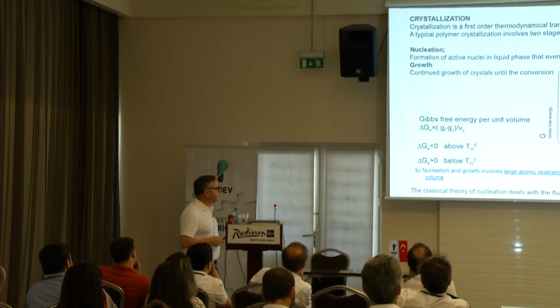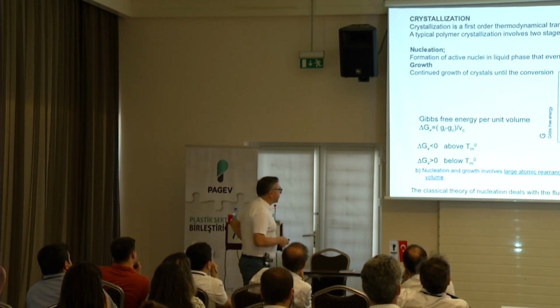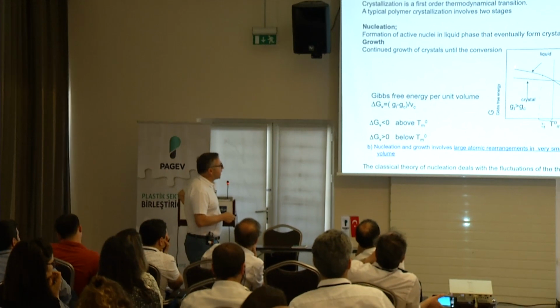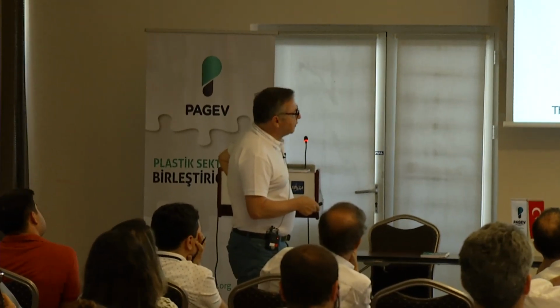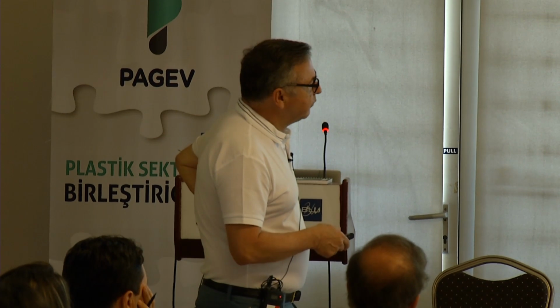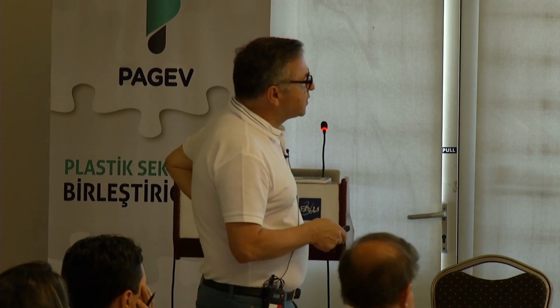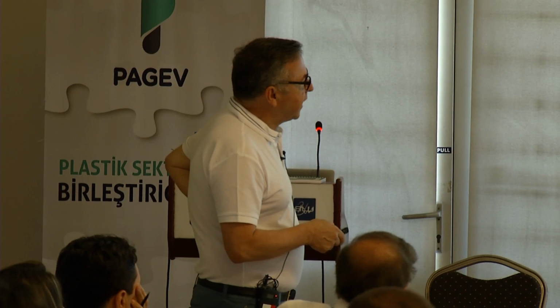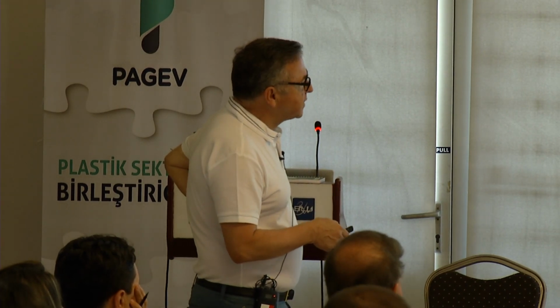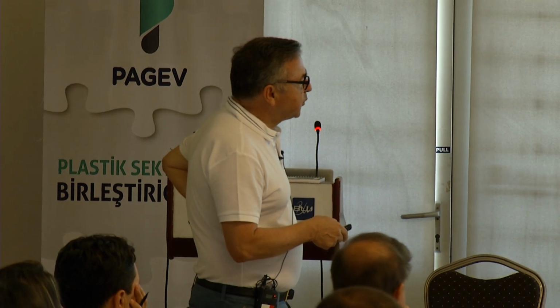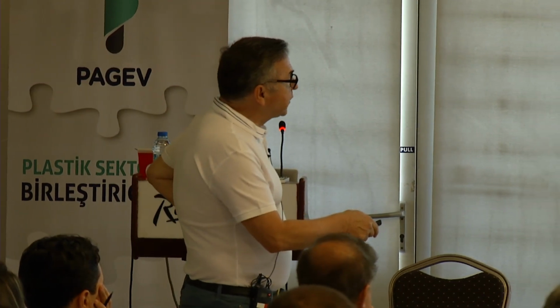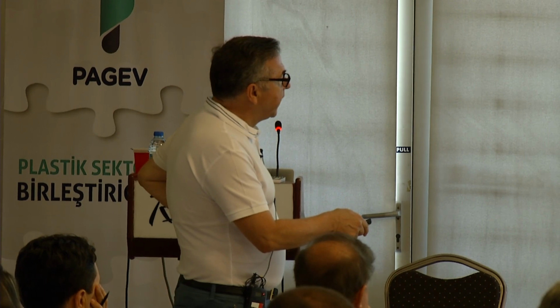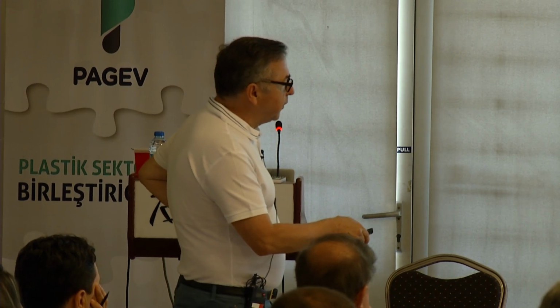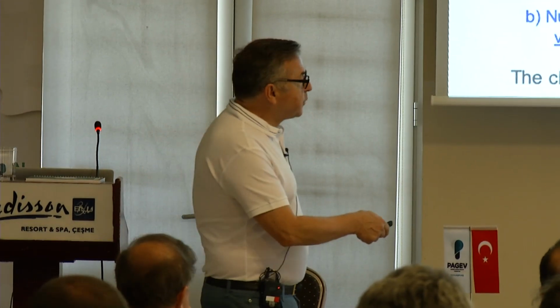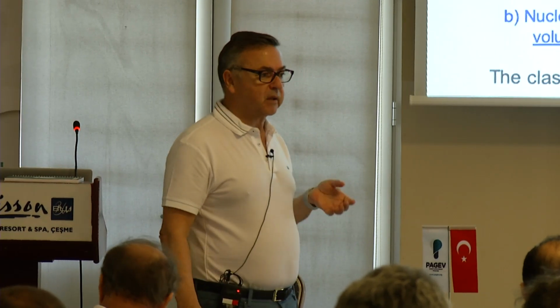So free energy is a very simple concept. The typical polymer chains in the liquid follow this kind of curve, a sharper curve, liquid. And the crystal has a more shallow curve, and at some point, this is the temperature axis, they meet at that point. So the difference between the crystal and the liquid free energy becomes 0. So we define that as a melting point, okay? And this happens to be T_m^0, that's an equilibrium melting point.